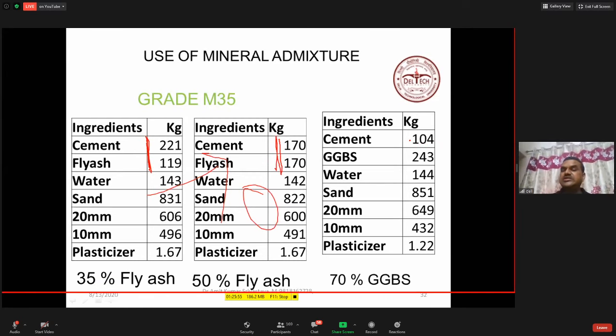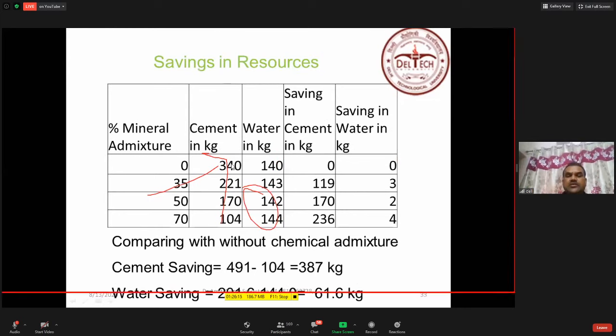And sometimes if I am using GGBS, our IS code allows 70% replacement. So if I replace 70%, then the OPC requirement is 104 and the GGBS requirement is 243. You see, we started from 491 and we can reduce up to 104. So now if I talk about the savings, 35%, 50%, 70% savings. If I talk about the saving only in terms of mineral admixtures, when there is no mineral admixture, your cement was 340 kg. When 70% mineral admixture, your cement was 104 kg. So the net saving in cement is about 236 kg if you are using 70% replacement.